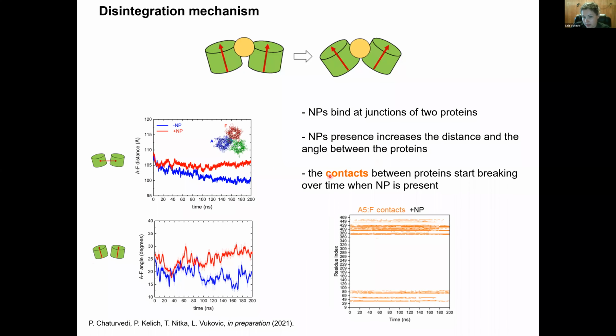We also tracked the contacts that the proteins form with each other. And when the nanoparticle is present, these contacts start breaking apart. The nanoparticle leads to the breaking of the contacts. Here we track over time the contacts between protein 1 and protein 2. The orange color signifies that there is a contact between a certain amino acid of these proteins. And you can see that over time, at the end, there are multiple contacts that get broken.